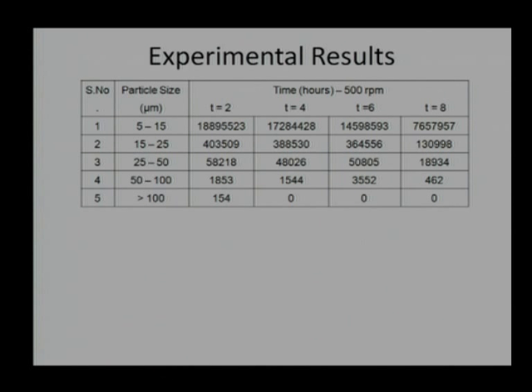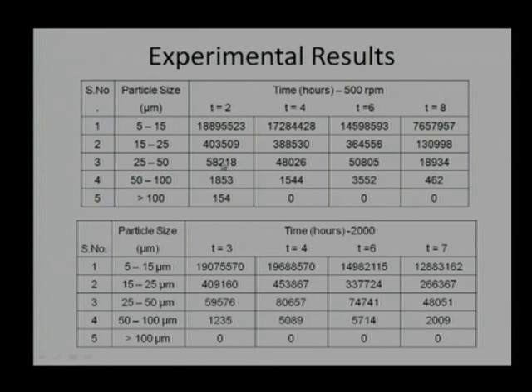We can say the starting case may be severe wear, but it is still in a controllable case. It is moving toward the mild domain or mild wear side. An interesting thing is that we found a couple of particles having size more than 100 micron. And when we studied the mild wear and severe wear, we said that about 20 micron particles, it is severe wear. So, for most of the domain in this case, it will be severe wear, but it is not uncontrollable. It is controlled, it is moving in the right direction. That means we do not have to worry too much, and we know this is running-in time, a bedding-in time, where particles will be larger initially. This is for 500 RPM.